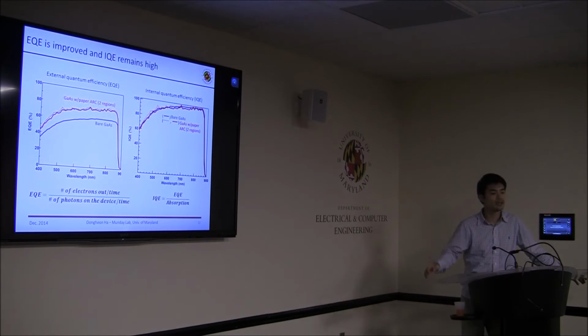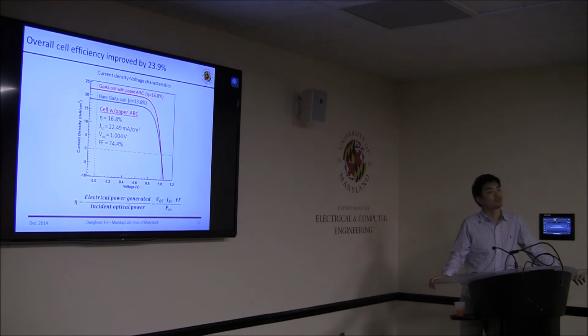Because that is the solar cell's own property, there should be no change regardless of the attachment of the ARC. So before and after the attachment, we have shown that there is no change in the IQE. Finally, we determined the current-voltage characteristics, and there was around 24% enhancement in the power conversion efficiency with the attachment of the paper ARC.